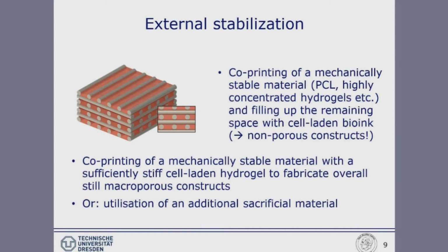Another possibility is... or I have to mention before, the maybe negative side effect of this approach is that if you really use a very soft cell-laden hydrogel, you end up with a non-porous construct. You are printing a porous, for example, PCL-based scaffold. So the grayish strands here are the PCL strands, but then all the pores, all the macropores are completely filled up with a cell-laden hydrogel. And therefore your final object is non-porous.